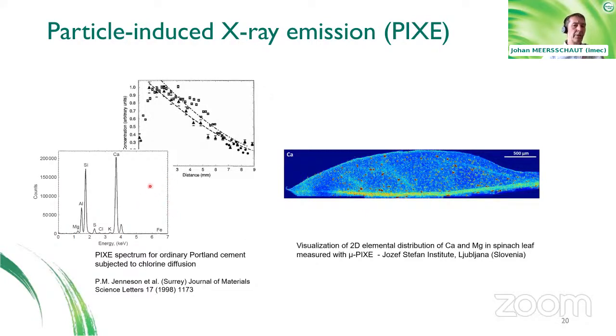And here I quote two examples where PIXE has been applied to investigate, for example, materials for construction. On the left, you see the PIXE spectrum of mortar. So this is Portland cement. And the idea there was to study the influence of the environment on the stability of the Portland cement. And one of the factors that is very important for the stability of the cement and the longevity, the lifetime of the cement, is the penetration of the chlorine. So this study, which was done at Surrey University, shows that the chlorine can penetrate as a function of depth, as a function of time.